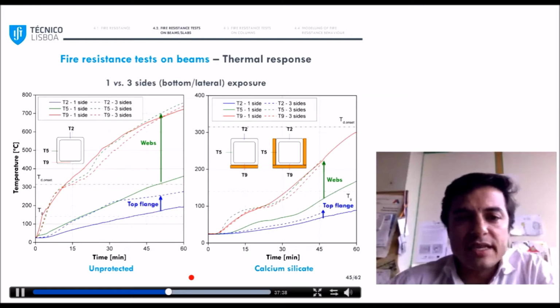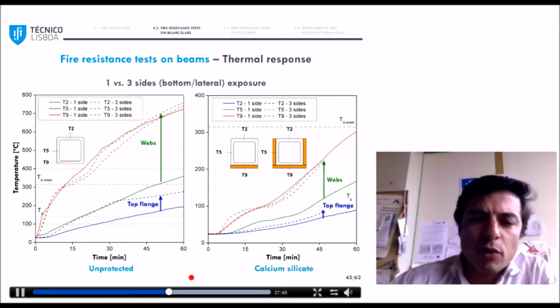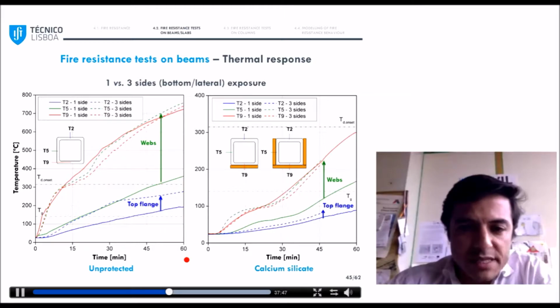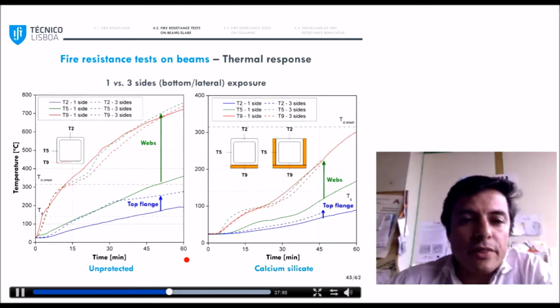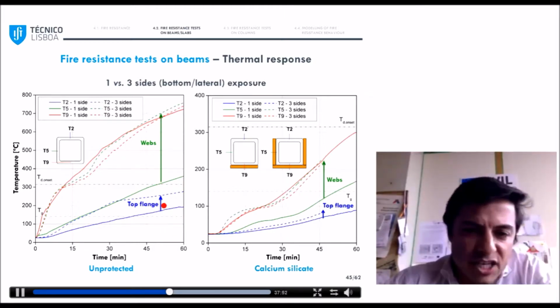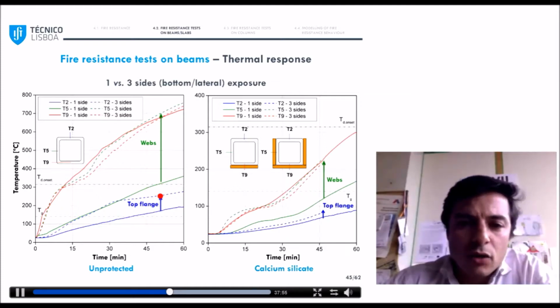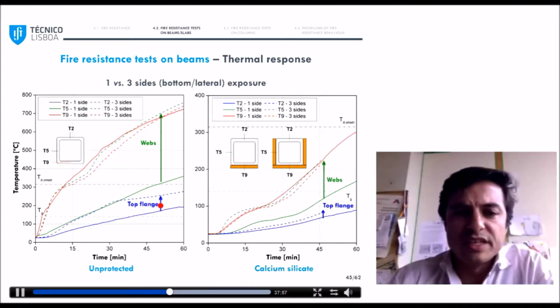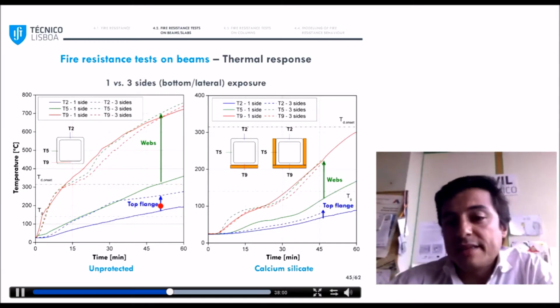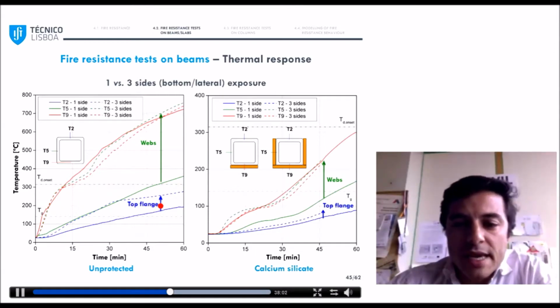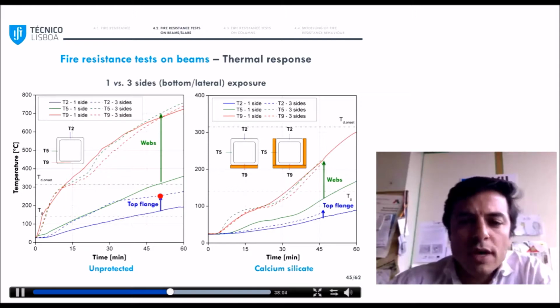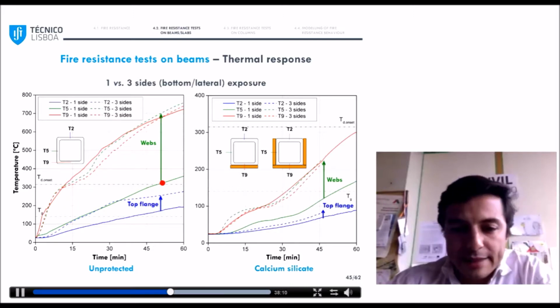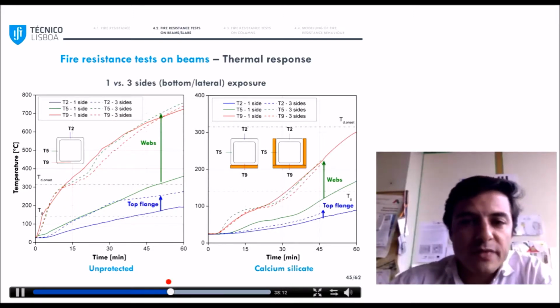Now for 3-side exposure, you can see here the influence of changing the type of exposure on the temperatures for both unprotected and protected beams. So as expected, for 3-side exposure, which are the dashed curves in this plot, compared to 1-side exposure, the continuous curves, you can see that there was a considerable temperature increase in the top flange in blue, and especially in the webs in green that were now directly exposed to heat.